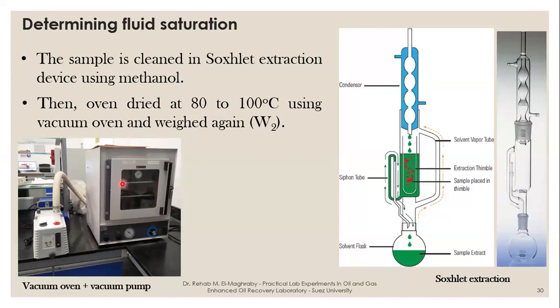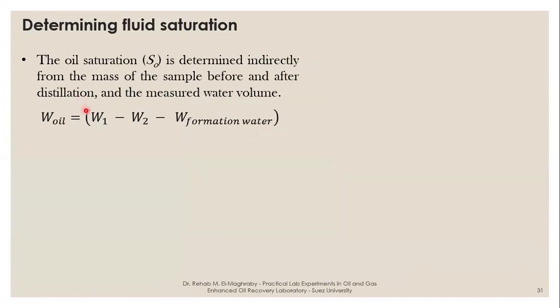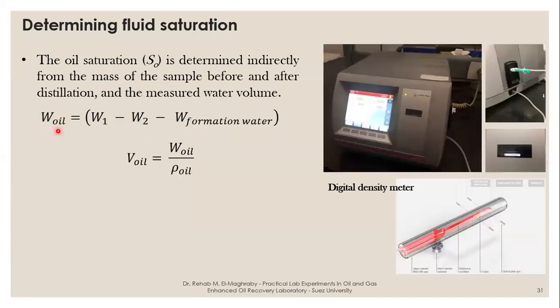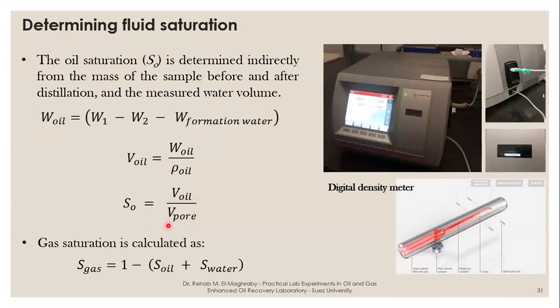So now you clean the core and leave it to cool down, and then you weigh it. So this is W2. Using the equation W1 minus W2 minus the weight of the formation water, now you can know the weight of oil. If you know the density of oil, we already discussed how we measure the density, you can know the volume of oil. You can calculate the saturation of oil, volume of oil divided by the pore volume. For the gas saturation, because we said that saturation of water plus saturation of oil plus saturation of gas all together equal 1, saturation of gas equals 1 minus saturation of oil plus saturation of water.